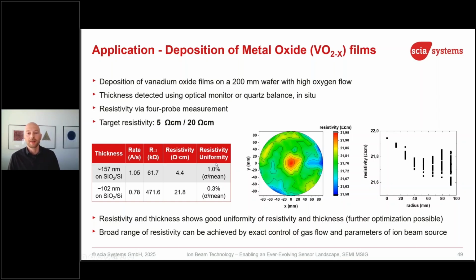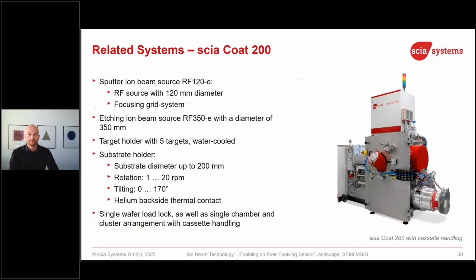Here we see some examples. Finally, we measure the resistivity of our vanadium oxide layer on a 200 millimeter wafer, and the total resistivity variation is 1%, 0.3%. So it looks very good. And that's also reproducible, of course, in volume production. That's the main point here. With magnetron sputtering, it's difficult to control this poisoning of the target itself. The tool we are using is also available in volume production, as mentioned.